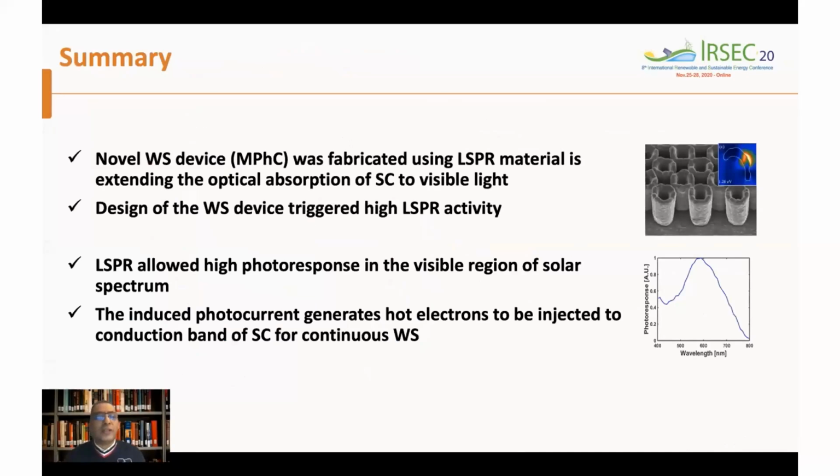I hope I convinced you that we are able to design a new device using LSPR material and semiconductor material, and we were able to extend the absorption from UV only to the whole visible light. The design of our structure helps us make light trapping, and this makes a high photoresponse in the visible region, which is due to localized surface plasmon resonance activity, as we showed.